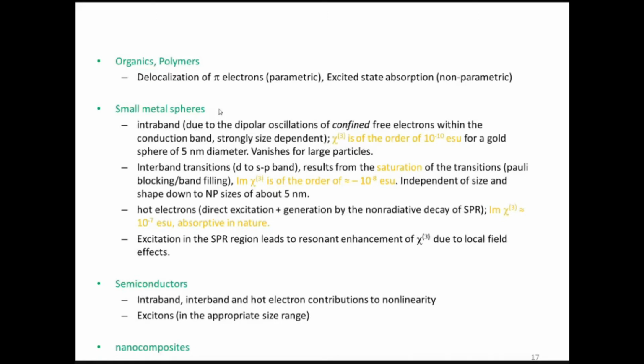And small metal spheres are very interesting. Metal nanoparticles, a lot of people work with metal nanoparticles. So in metal nanoparticles, we have four kinds of transitions basically. There are intraband transitions, interband transitions, hot electrons, and excitation of the surface plasmon resonances if you are in metals, particularly noble metals. So intraband transitions are dipolar oscillations of confined free electrons within the conduction band.